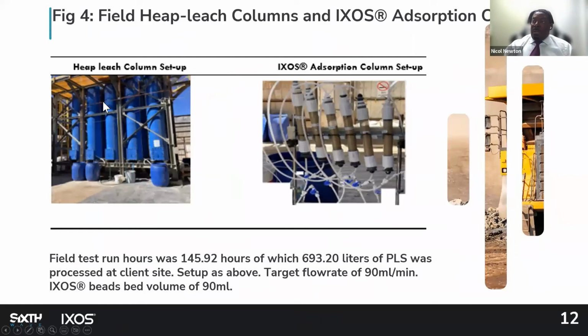So on the field, we had 12 tanks of heap columns set up to recover close to about 60 liters per day. Now with the field test, we ran 145 hours and we recovered 693 liters of PLS, and we used 90 mils per minute of flow through the adsorption columns. The adsorption columns, we had 90 mils of IXOS® beads set up in the columns.